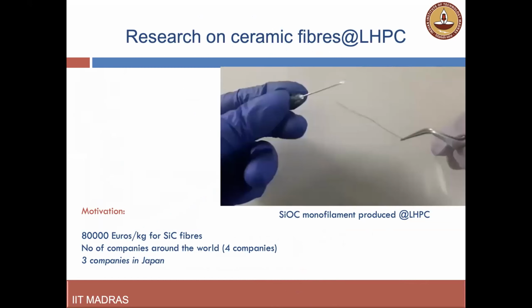Last but not the least, we have now been focusing a lot on ceramic fibers, and we are primarily looking at structural fibers. What is the motivation? The motivation is simple. Silicon carbide fiber was first produced by Yajima in 1975, but India is not able to make silicon carbide fibers yet, which means we are not able to go to 1800 or 2000 degrees Celsius ceramic composites in our space applications. We are not able to do it, because silicon carbide fiber is under embargo. Nobody sells it to us, and it's extremely expensive as well.